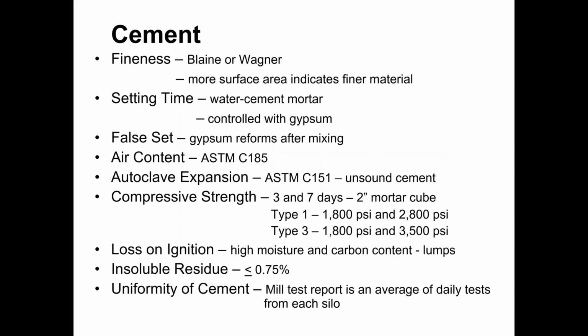All right, setting time. This is the time that it takes a water cement mortar to reach initial set. Just as a reminder from level 1 and level 2, initial set is when the concrete achieves 500 psi. So the setting time shown on the cement mill report is the time for a water cement mortar, so it doesn't have any aggregate. The setting time is controlled by the cement manufacturer by adding gypsum. Remember when we looked at the manufacturing process, close to the end during final grinding is when the gypsum was added to the concrete. So based on the performance of the cement, the amount of gypsum that is going to be used will vary. The cement manufacturer will determine that value based on the setting time tests that they are conducting.